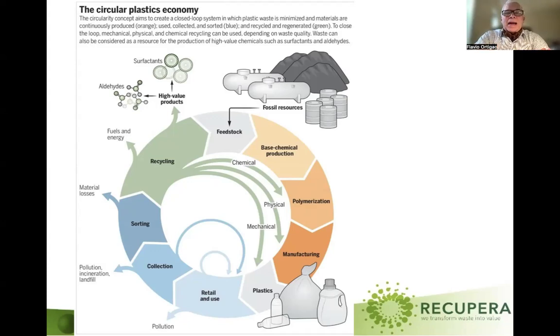This is what makes plastic recycling very tough, because they are not pure materials. They are mixed materials from the beginning. And it's not only about cleaning the product, because the plastics are hydrophobic and they will absorb all kinds of materials they transport or come in contact with into their polymer constitution. So you cannot really wash out the contaminants. That is a big problem. It's very difficult to wash out.